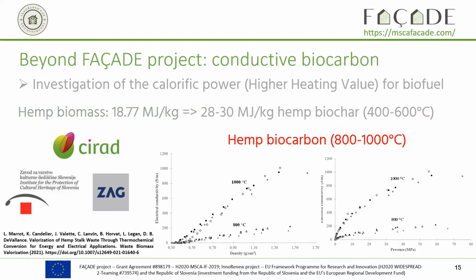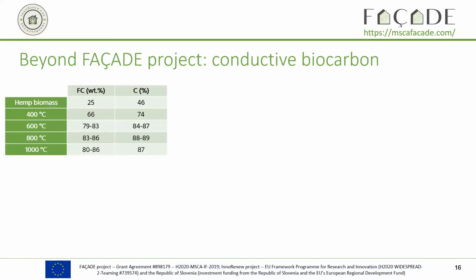Then we looked at the conductivity properties of the biocarbon, and we saw that up to 600 degrees we observed very, very little conductivity. But when we carbonized at 800 degrees and above, at 1000 degrees, we got biocarbon that started to be really conductive. And we looked at the properties and tried to understand what parameter was bringing this conductivity to the biocarbon.